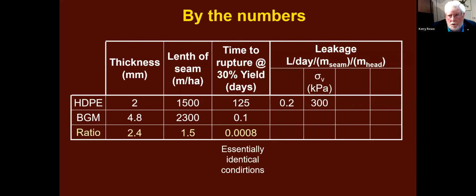Next, let's look at leakage. We've done the same types of tests with geomembranes, with welds that are defective on HDPE geomembranes. We've done them on BGMs without defective welds and with not 100% welds in the 80 to 90% range. And the extreme case we've looked at for polyethylene is one that wasn't welded at all. And so we can compare the leakages on as similar cases as we've got. We don't compare the same cases because we just didn't have the data.